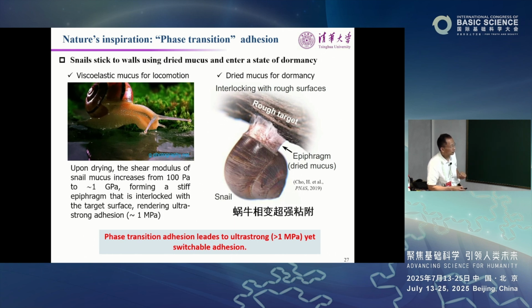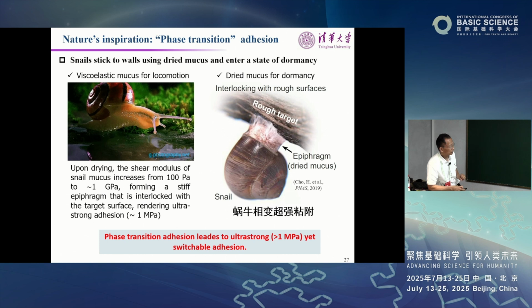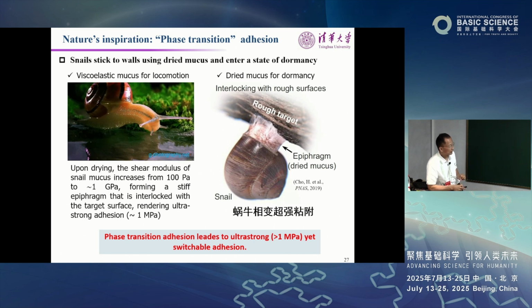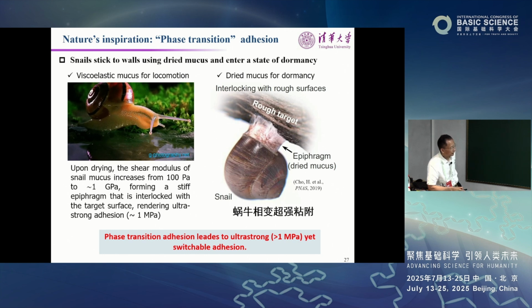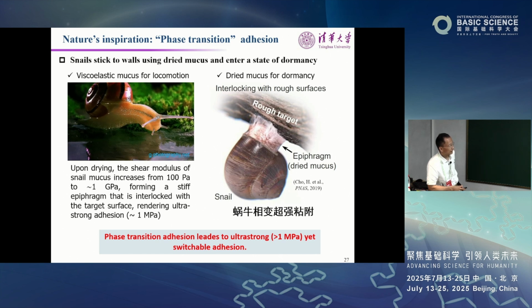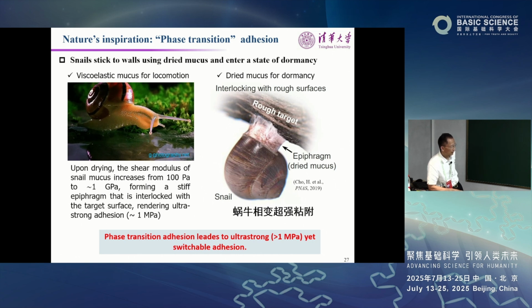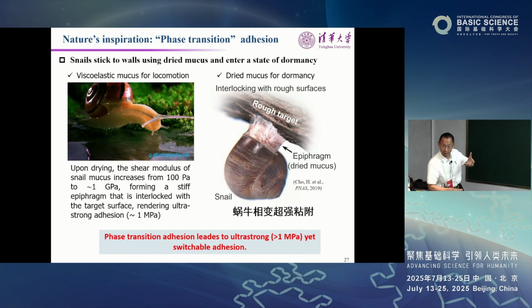But when it wants to attach to the surface, then it dries out. Okay, it has dried mucus. So mucus becomes a solid. When it's moving, it becomes fluid. But once it adheres, right, when it goes into hibernation, it dries out. So this in solid form is a strong adhesion. In the fluid form, it's weak adhesion. This is called phase transition adhesion. So phase transition adhesion leads to pretty strong adhesion, which has been measured over 1 megapascal stress, and it's switchable in the sense you can do the phase transition, right? If it's a solid, it's strong, if it's a fluid, it's weak. So it's strong and switchable.